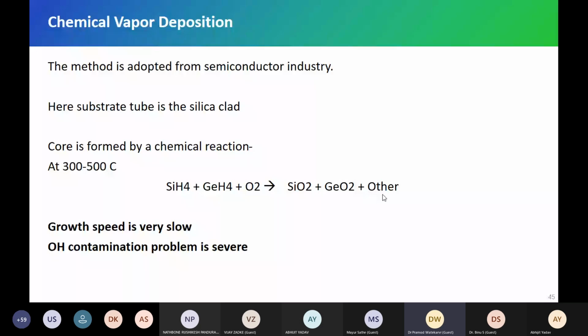The only thing with this method is that it is very painful to wait. We take SiO2 or some substrate and keep it, and then on the substrate we start the machine and flows, and we set everything on the computer, the flow rates, and at the end in the morning you will get 1 mm, 2 mm. So the thickness is very low. If you want more, then again we have to keep it there for 24 hours. If something happens in between, then it is spoiled.